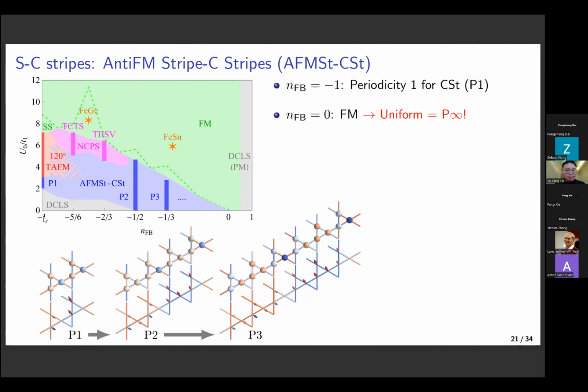Now, if we go from the empty filling to the half filling of the flatband, we know from previous slides that we're looking at the ferromagnetism. And we know that the ferromagnetism is uniform in the whole space. And we can think of it as a spin and charge stripe with infinite periodicity. So now we have seen that we have periodicity 1 at the -1 filling, and we have infinite periodicity at the 0 filling. And we may expect a gradual increase of the periodicity as we increase the filling from -1 to 0.